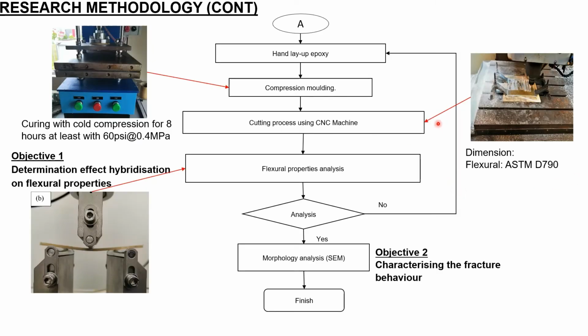After we do the alternation arrangement, next we hand lay out the epoxy, then compression molding. We cure the plate with a cold compression machine for at least 8 hours at 60 psi. Then after that, we do the cutting process using a CNC machine.